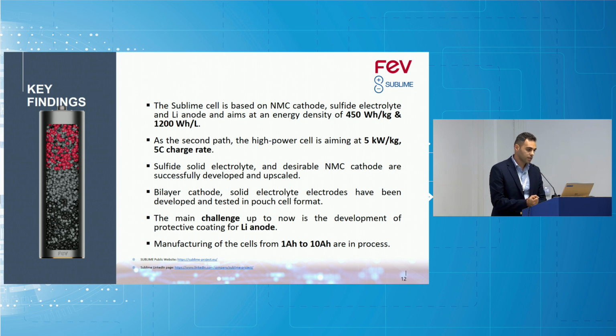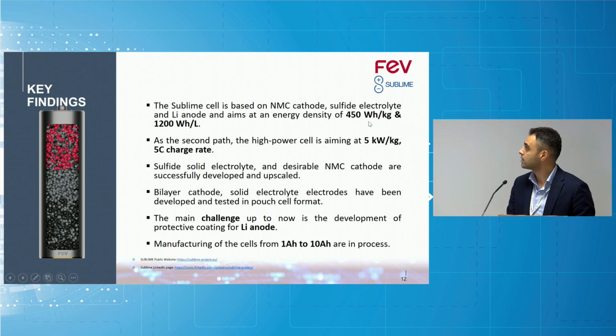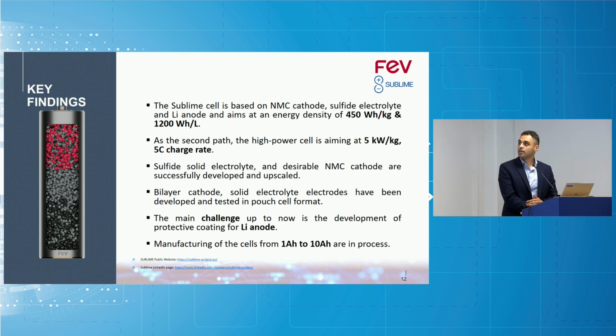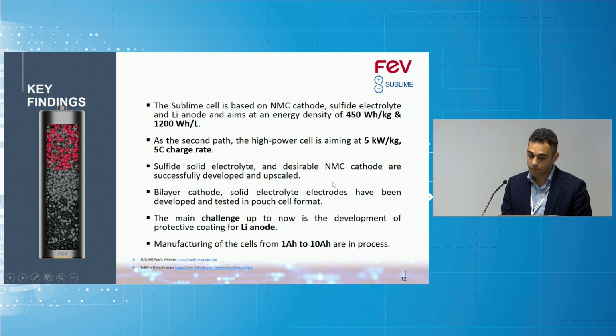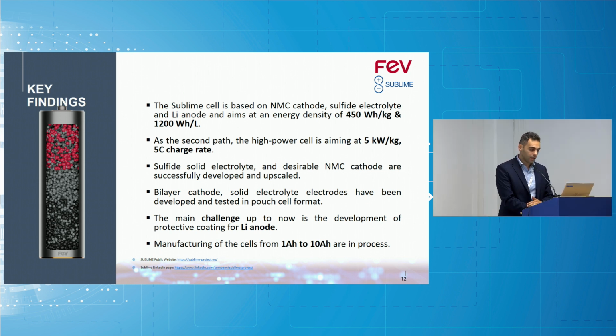So at the end, just to summarize, the aim is to make cells with an extremely high energy density, 450 watt-hour per kilogram. As I said, this can be achieved based on very extreme conditions. There are some activities on providing at the second path. We have the cathode and solid electrolyte ready for this. I'm working on making a lithium anode ready for this path. And as I said, sulfide electrolyte NMC cathodes are developed and upscaled, and bilayer cathodes are also produced, and the initial pouch cells are fabricated.